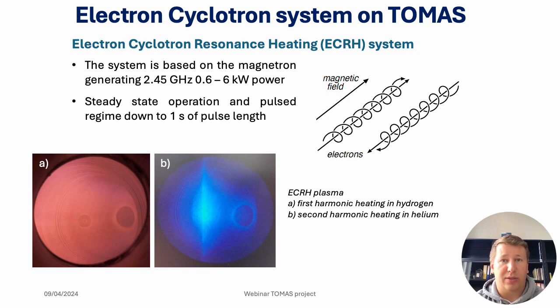Depending on the plasma parameters, we can either create strong ion fluxes towards some part of the wall or charge exchange neutral particles equally distributed to all wall surfaces. These generated particles are used for impurity and fuel release in the same manner as glow discharge cleaning. Understanding all mechanisms of wave absorption and propagation is important for regulating particle fluxes and energy and minimizing adverse effects,